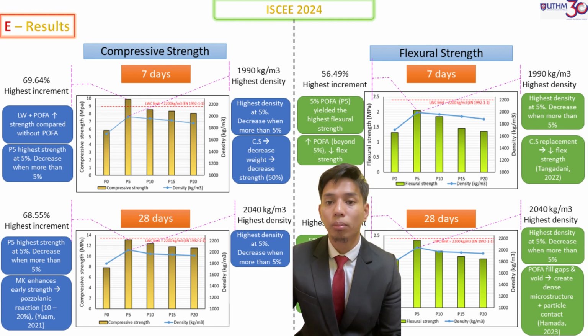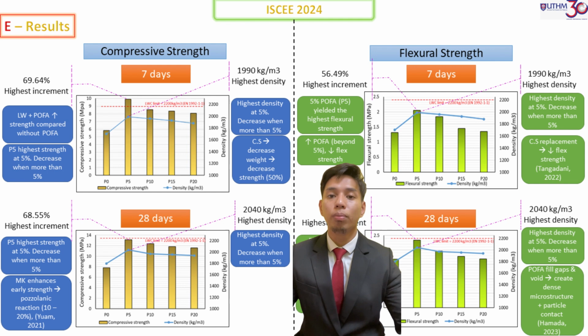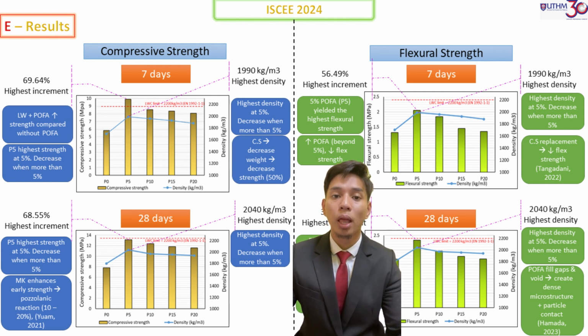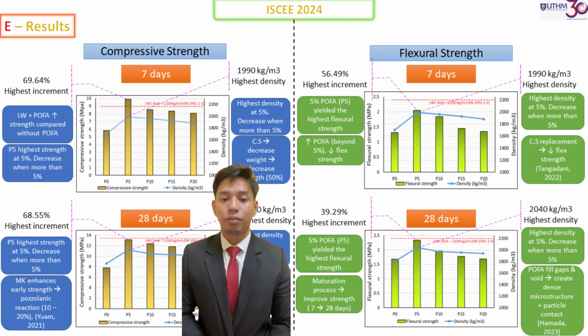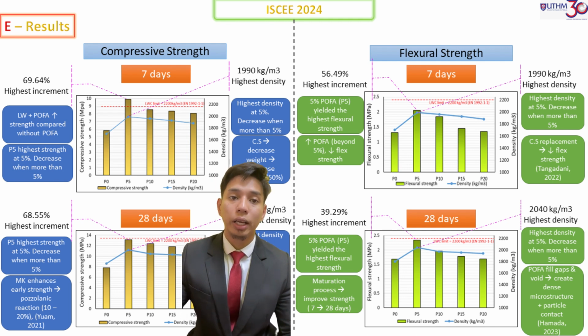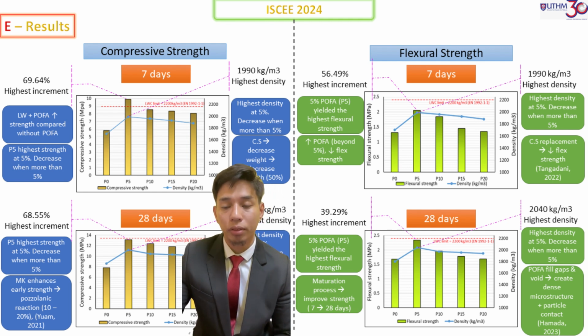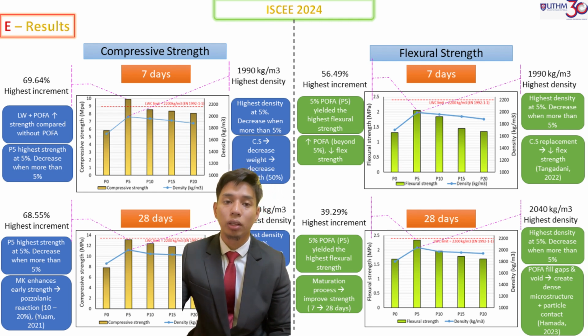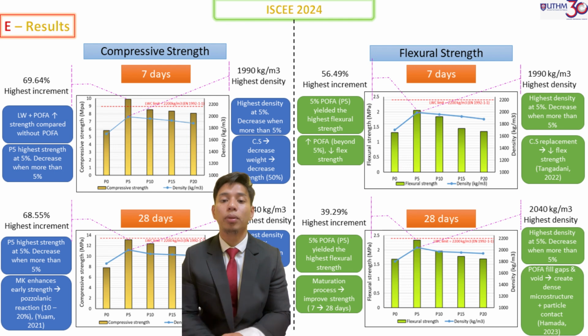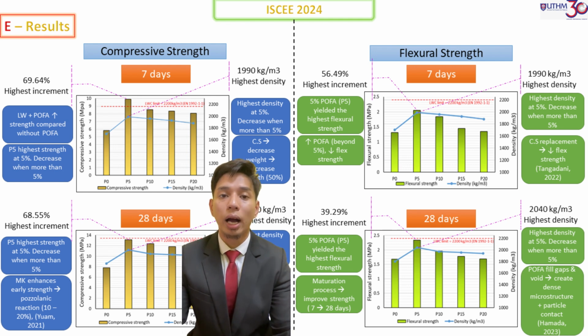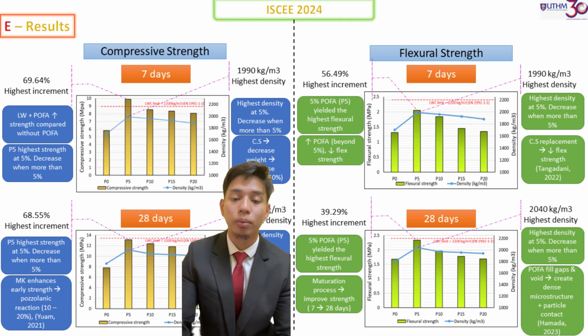Replacing more than 5% of cement with POFA will reduce the compressive strength because POFA's porous nature makes the mix harder to compact, creating more voids. So next is the flexural strength. At 7 days, the highest flexural strength is recorded at P5 also, 5% of POFA as a partial cement replacement, with a 56.49% increment from the P0.